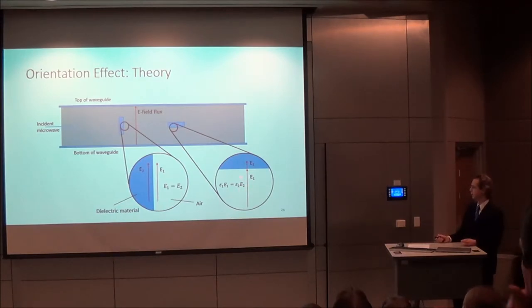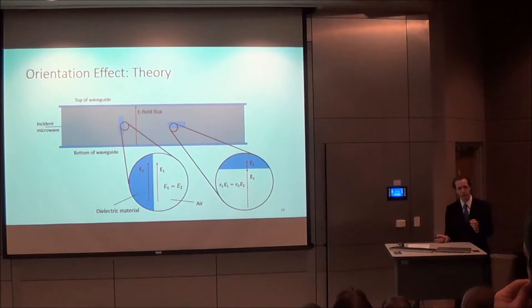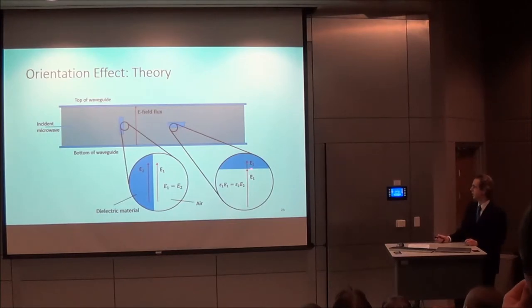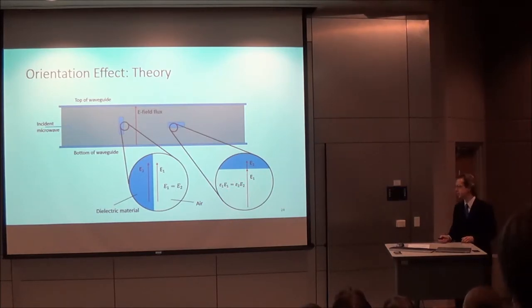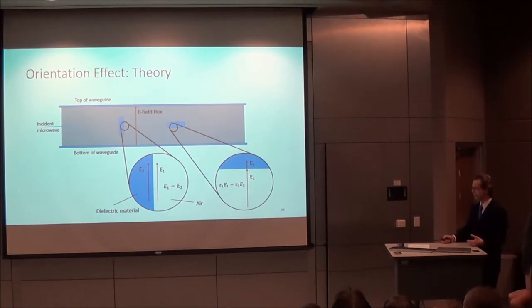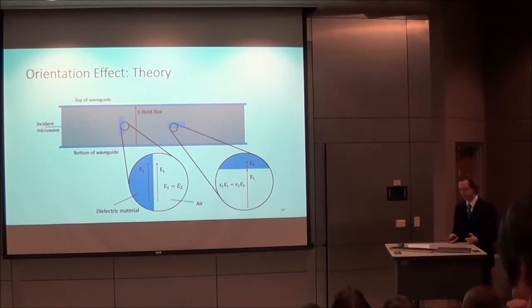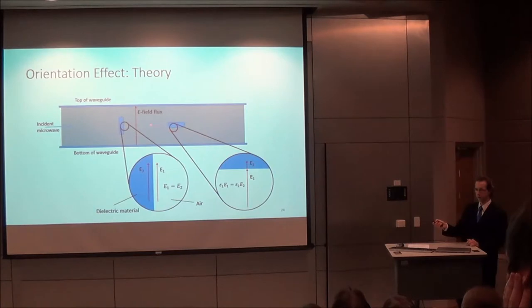Where the flux lines are perpendicular to the dielectric interface, however, the electric field intensity in the dielectric target will be reduced by a factor equal to the ratio of those two permittivities. And since the permittivity of a dielectric material will be greater than air, there will be a significantly lower intensity of the electric field strength in the target. This means that the vertically oriented target will heat much more readily than the horizontally oriented target.